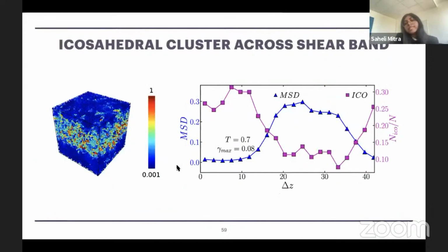Like before, in the case of a shear band, we can locate the shear band by computing the mean square displacement of the particles from one cycle to the next. If we bin the system along this direction and see, for each bin, the percentage of the particles that have association to icosahedral clustering, we see that outside of the shear band, almost 30% of the particles are associated with icosahedral clustering, whereas inside the shear band, this percentage is negligible. This is very interesting because we can now precisely see that in the presence of a shear band, we definitely have different local environmental structure inside and outside of the shear band.